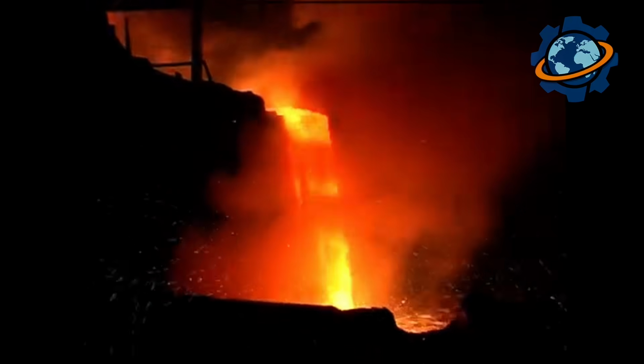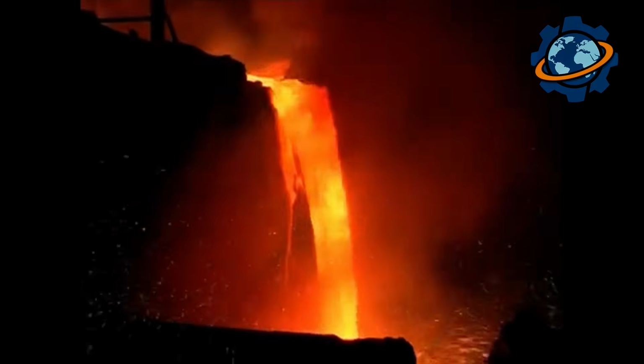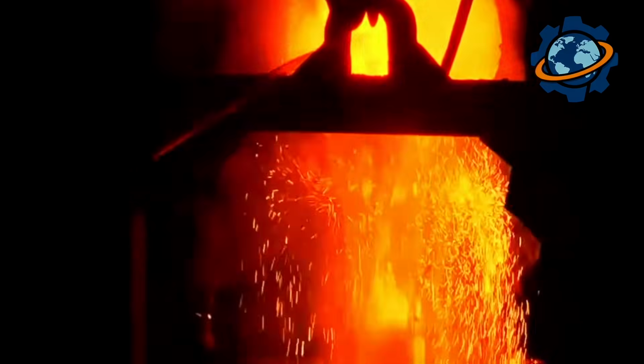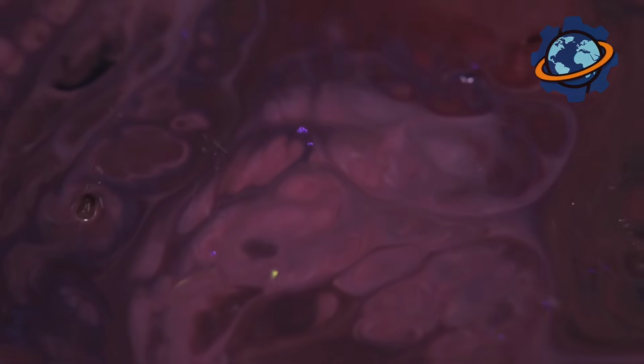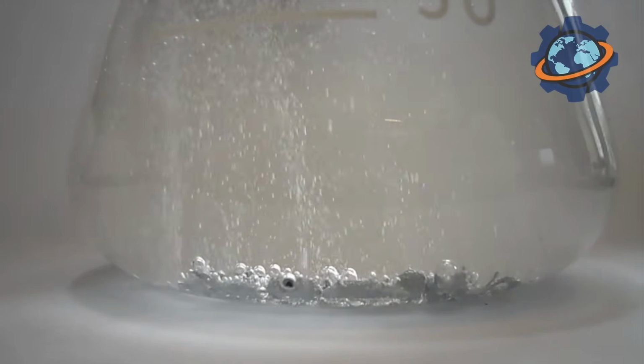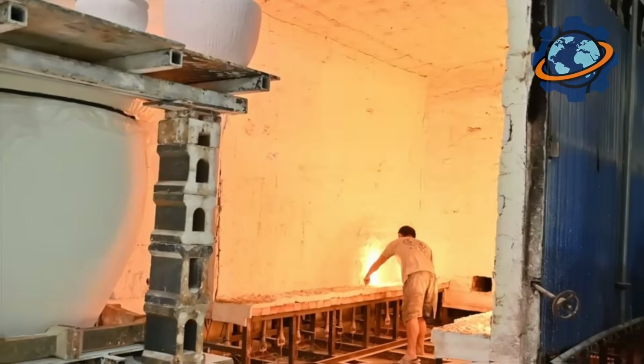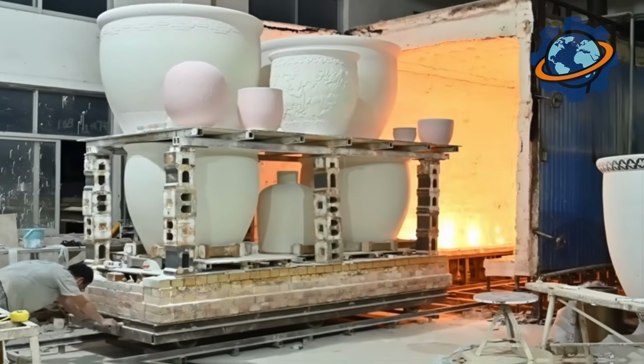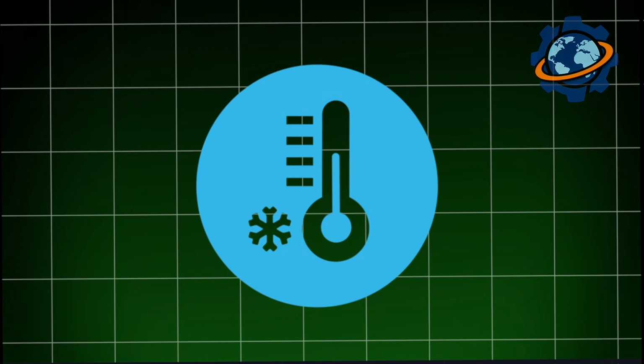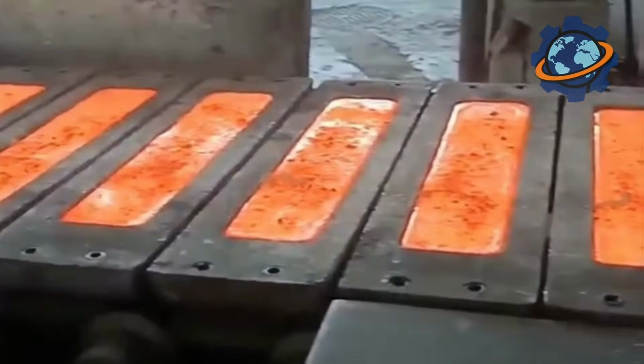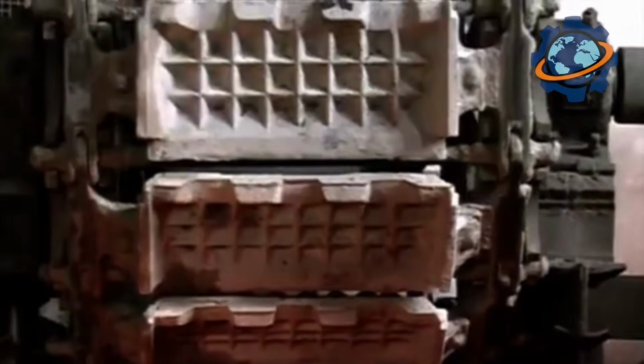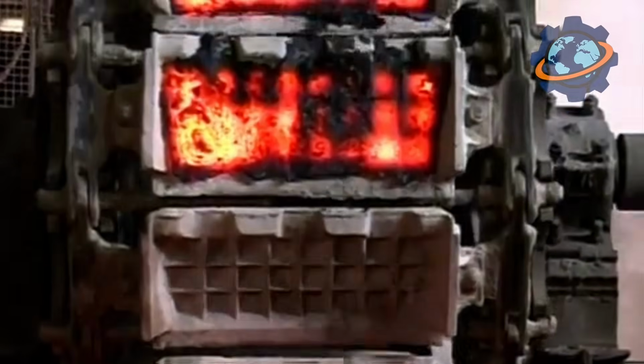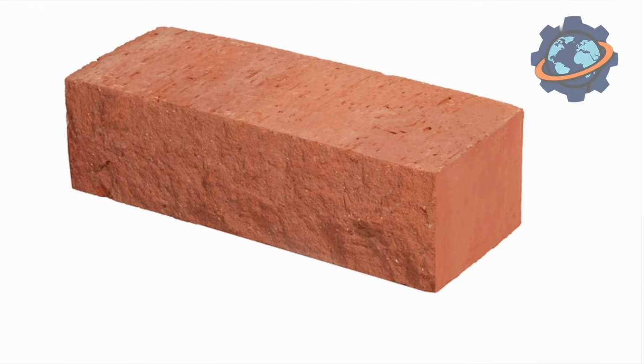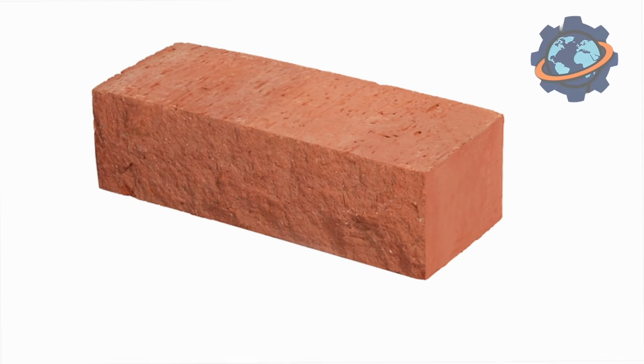At such temperatures, complex chemical reactions are triggered, mineral particles soften on the surface and sinter together, forming a strong and dense ceramic structure. In the system of aluminum oxide and silicon dioxide, new crystalline compounds are formed. In particular, needle-like crystals of mullite, which, like reinforcement, permeate the entire structure of the brick, giving it exceptional strength and thermal stability. Having passed the peak of heating, the brick just as slowly passes through the cooling zone. This stage is no less important, as rapid cooling would cause thermal shock and destroy the product that has just gained strength. At the exit of the kiln, a completely new product appears. A hard, ringing, slightly rough to the touch block that is not afraid of fire.